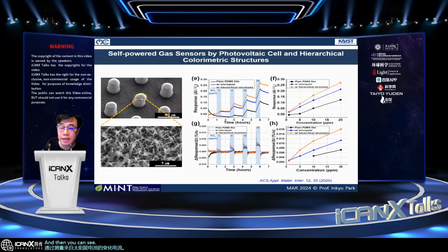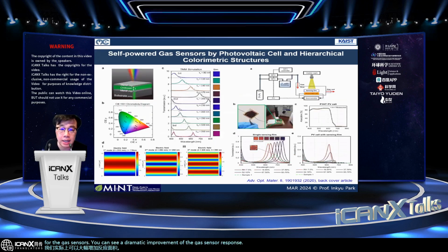And then you can see that by using the hierarchical structure using microposts and nanowires, we can dramatically increase the reaction area for the gas sensor. You can see a dramatic improvement of the gas sensor response. A little bit of modification, but with a similar method.